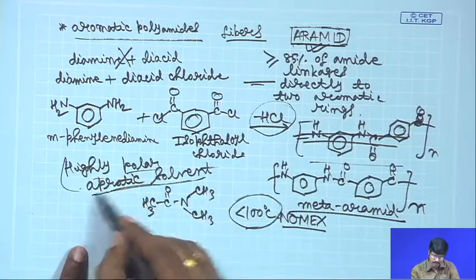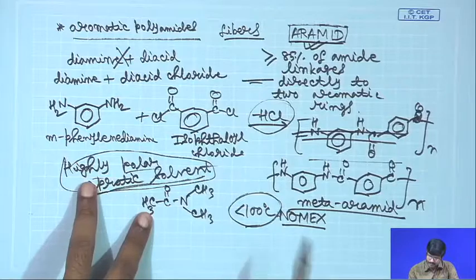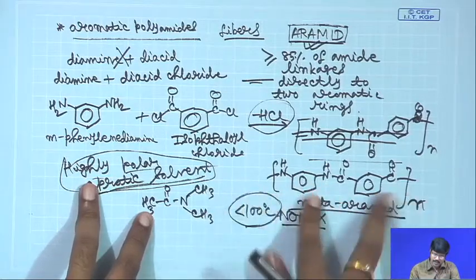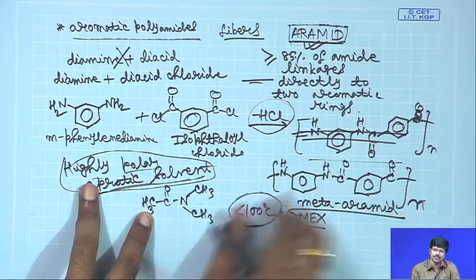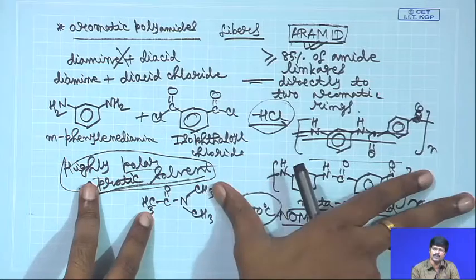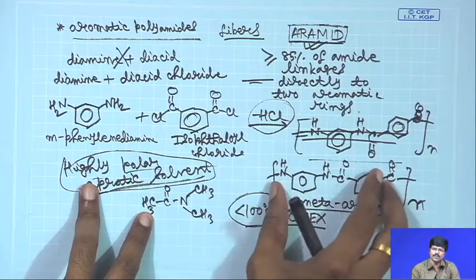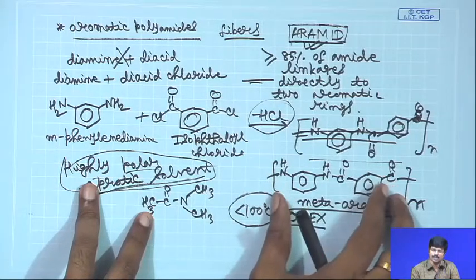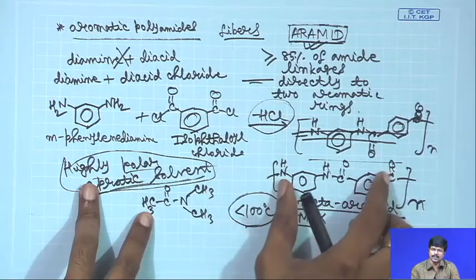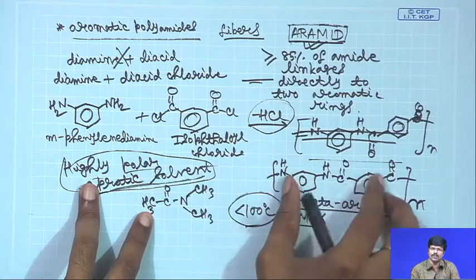and the choice of the solvent is dictated by the fact that the growing polymer chains should not precipitate out before the polymerization has reached the intended molecular weight. Remember that your temperature here is low, so the solubility of this material might be lower in the solvent. So, if that is the case, then it can prematurely precipitate out before a high molecular weight is reached.